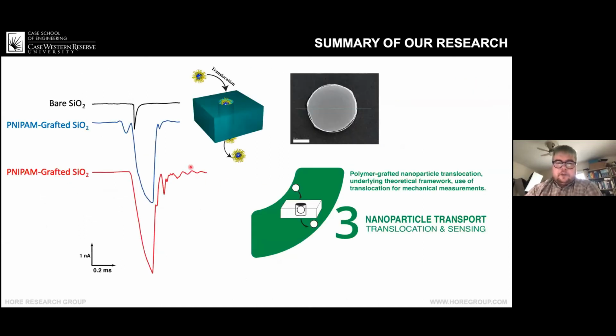We also look at nanoparticle transport. So we look at the transport of nanoparticles through single confining nanochannels. I've shown it schematically here, but here's a TEM image of what the nanochannel actually looks like. And these have diameters anywhere from 40 to 100 nanometers and lengths of about 100 nanometers. And what we record is the ionic current through the channel as a function of time, and we get these characteristic resistive pulses due to the blockage of the current through the pore. And then our goal after that is to analyze these pulses to understand what's going on in terms of the transport of the nanoparticles.